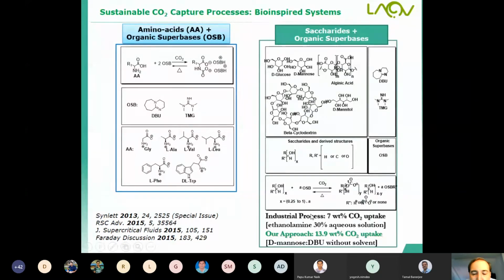The industrial process uses ethanolamine, 30% in aqueous solution. This is a corrosive solution, and the best result reported normally in the literature is around 7% of CO2 uptake. Our best approach until now is around 40% of CO2 uptake, using a very simple combination, the D-mannose and DBU without solvent. And this is something that we are trying to explore in more detail.